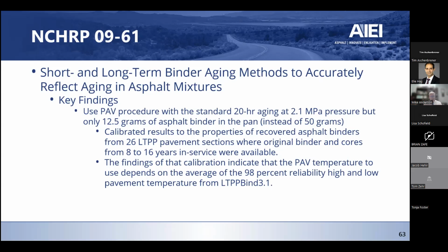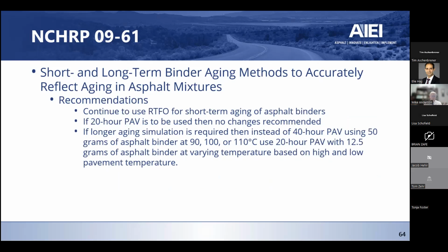They did calibrate the results to the properties of recovered binders from 26 LTPP sections, with cores between 8 and 16 years of service. They were able to calibrate that to determine what the PAV temperature and the aging would look like. They were careful to say that if you're using RTFO, you really don't have to make any changes, and if you're sticking with a 20-hour PAV, you don't have to make any changes. But if you want a longer simulation, instead of doing the standard 40-hour PAV with 50 grams of asphalt binder, you use a 20-hour PAV with 12.5 grams of asphalt binder in it and slightly different temperatures.